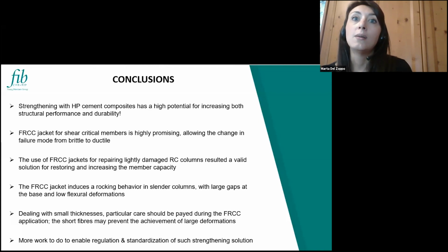When we deal with small thickness, we need to pay attention because sometimes really small asymmetries in the jacket can lead to a very different behavior in the positive and negative direction of the members. So a lot of attention should be paid during the application of such materials. And of course, the short length of the fibers and the strain softening behavior prevent the achievement of large deformation. So we cannot achieve very large ductility for these kinds of specimens. And of course, much more work needs to be done to allow the regulation and standardization of this technique to be used for the design of new strengthening solutions.